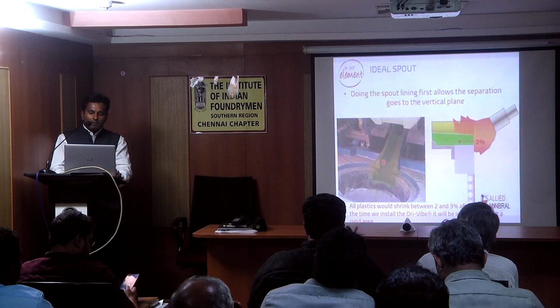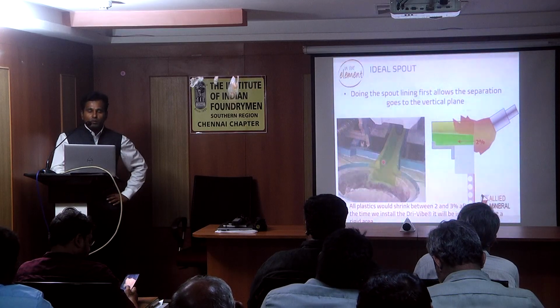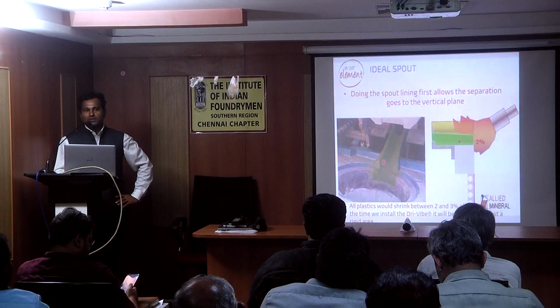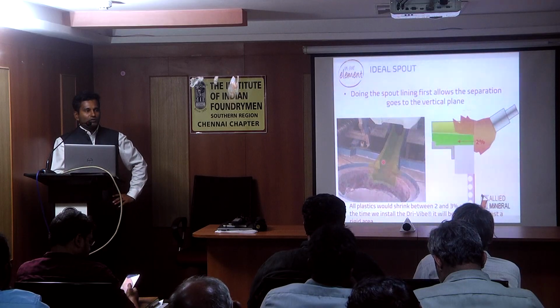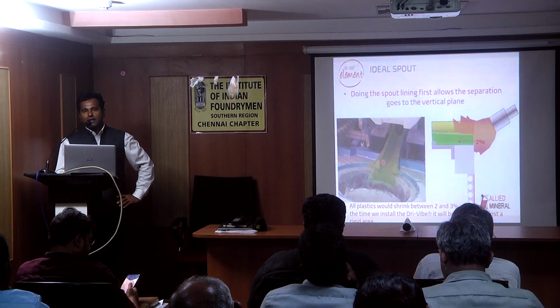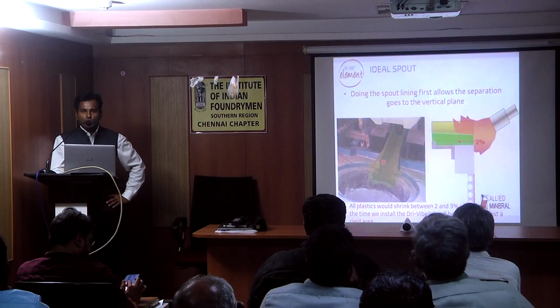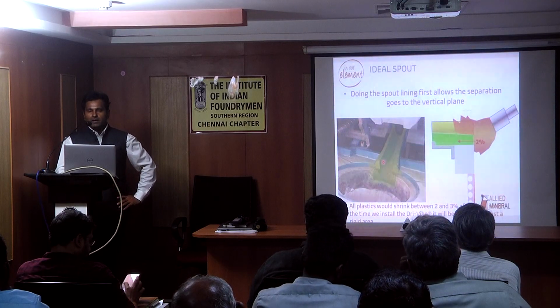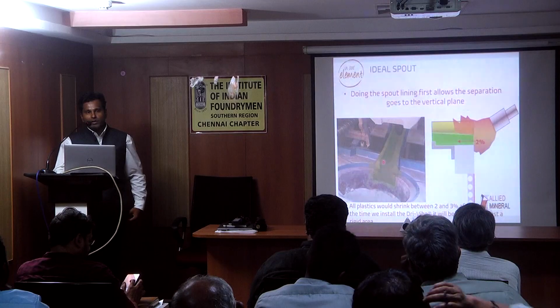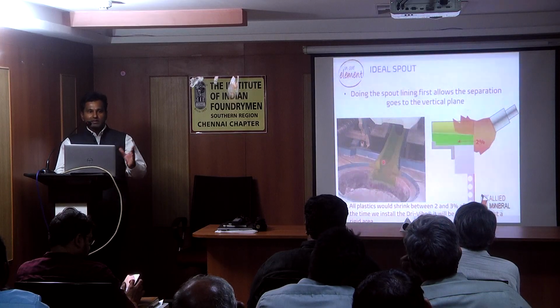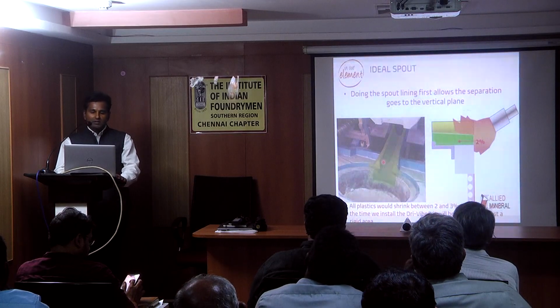We recommend a plastic refractory with a chrome oxide addition. This chrome oxide will give you the added advantage of non-wetting properties. So the metal and the slag don't stick to your spout, and even if the metal solidifies, you can easily remove it without damaging the lining of the spout.